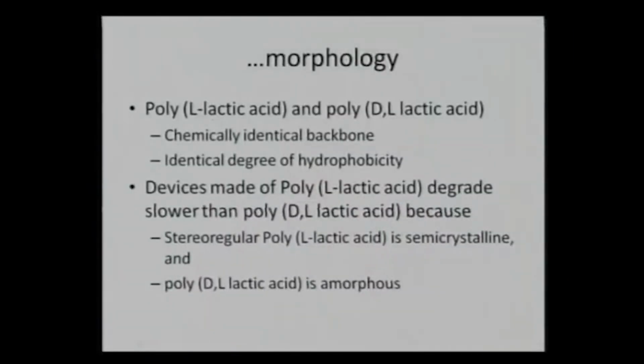Again, the morphology is very critical, because in the case of, say, poly L-lactic acid and poly DL-lactic acid, they have an identical backbone. So the overall backbone is very similar. They have an identical degree of hydrophobicity as well. So obviously we would expect that they should degrade at the same rate, because of similar chemical nature and similar hydrophobicity. But because of the difference in crystallinity, stereoregular poly L-lactic acid is semi-crystalline in nature, whereas poly DL-lactic acid is amorphous.